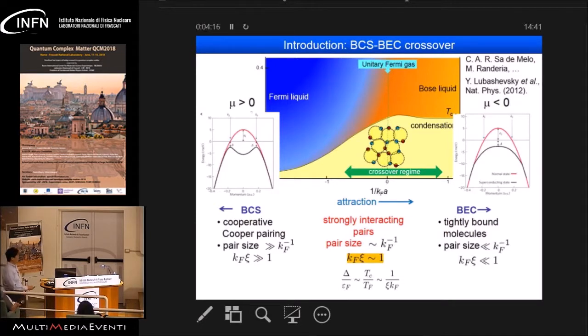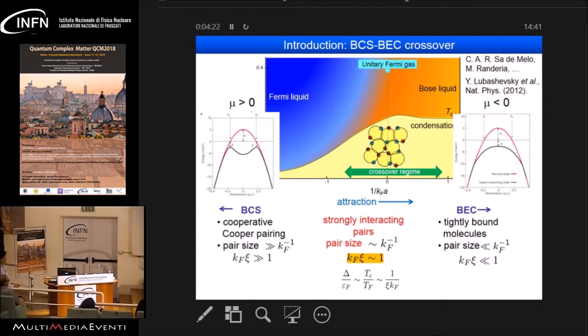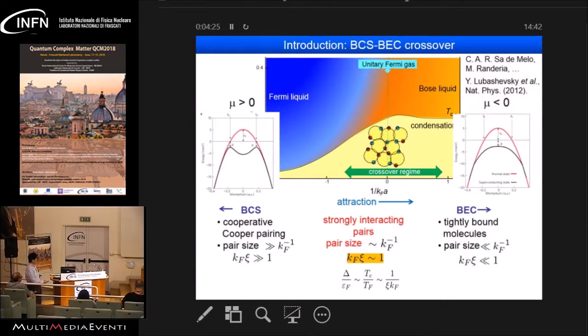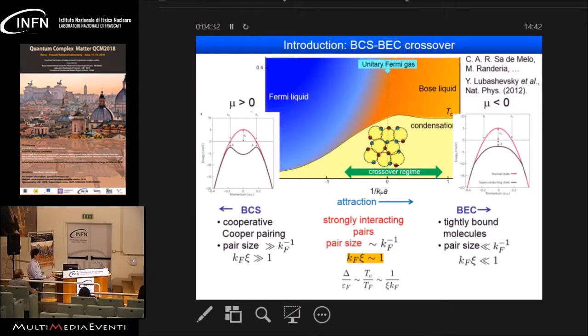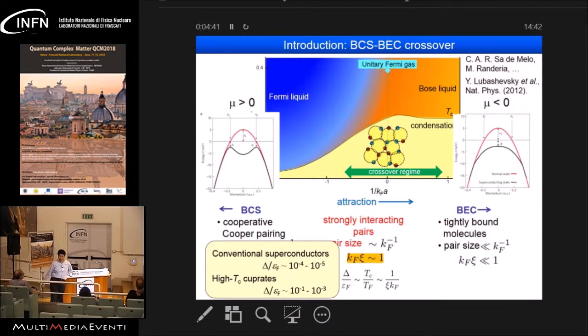Now, an important point here is that we have no phase transition between these two limits, so we have a crossover. The most interesting part is the so-called unitary limit, where we have strongly interacting pairs, and kF xi is of the order of unity. One important parameter here is the ratio between the superconducting gap delta and the Fermi energy EF, which is related to 1 over xi kF. In conventional superconductors, this delta over EF is very small, like 10 to the minus 4 or minus 5. But in underdoped high Tc cuprates, this ratio becomes quite large. And there is a big discussion about the relevance of this BCS-BEC crossover physics in underdoped high Tc cuprates.